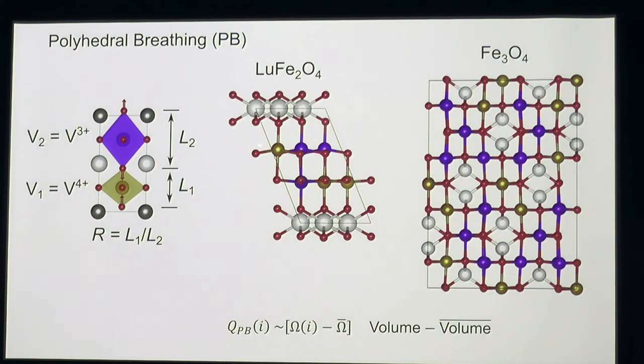Here, we should emphasize that because the atoms with different valence states are not orderly stacked as a superlattice structure, we can no longer use the R ratio to characterize the polyhedral breathing. We use another physical quantity, Q_PB, which relates to the difference between the volume of a specific octahedron and the average volume of the octahedra in the entire crystal. As a result, a smaller polyhedron will give a negative Q_PB, and a larger one will give a positive value.